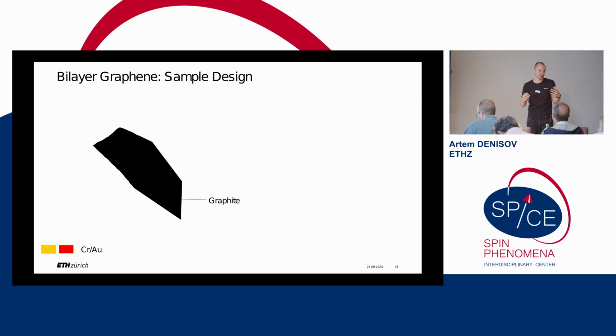Right. So before talking about how we form dots in the graphene, I will briefly walk you through how we fabricate the devices themselves. We use a pretty standard dry stacking technique using a PC-PDMS stamp. So we pick up flake by flake and eventually put the resulting stack on a chip and put some contacts to it. I will go in reverse. So we start with the graphite, which we use as a backgate.